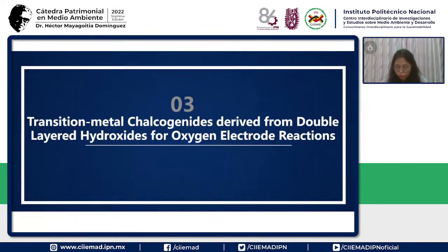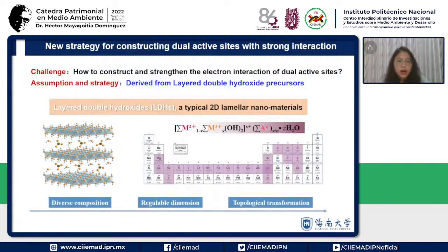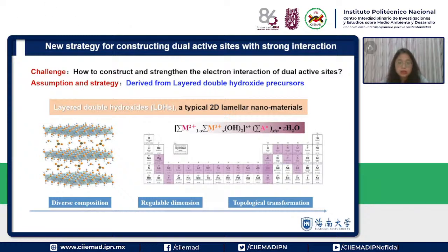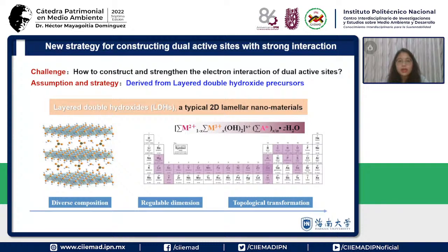And the next part, I'm going to report the work we are doing recently about this transition metal chalcogenides derived from the layered double hydroxides for oxygen electrode reactions. So now, for the ORR or the OER here, we know the single active site sometimes does not show satisfactory activity for the reactions. So when we construct the dual active sites, we need to increase the interaction between these two active sites. How can we construct and strengthen the electron interaction of these two dual active sites? And we assume and propose a strategy.